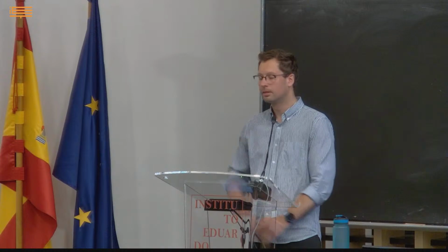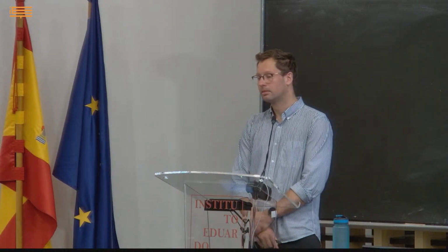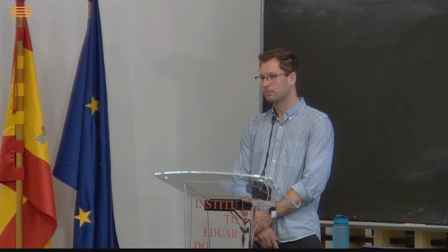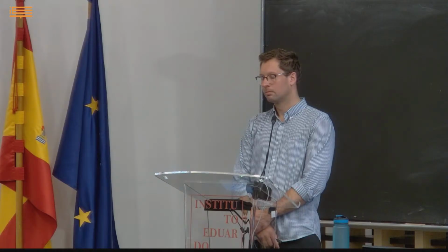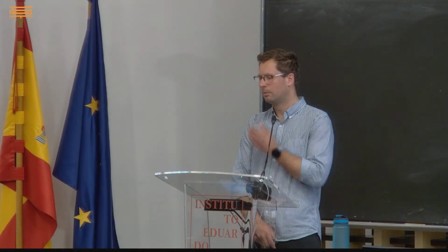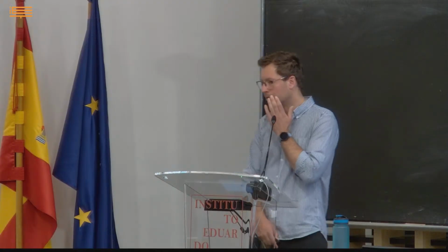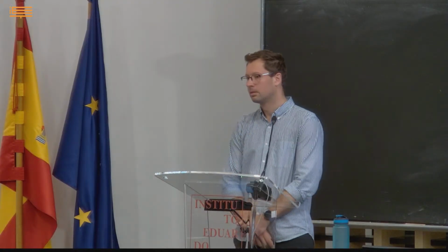Carbonation. When you observe the presence of Q3 in your sample, it is because you have more silica-rich material, from carbonation, or you lose calcium. In our material, we have Q3, Q4 because we have aluminium. That is my opinion. Why would alumina make Q3 and Q4s? I think it's a separate phase.